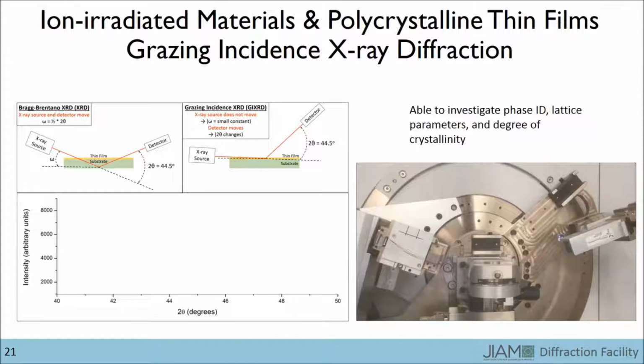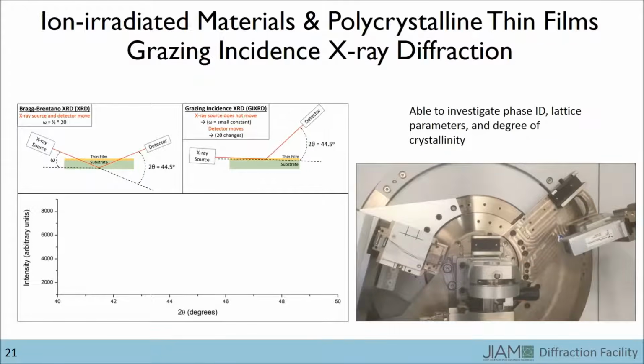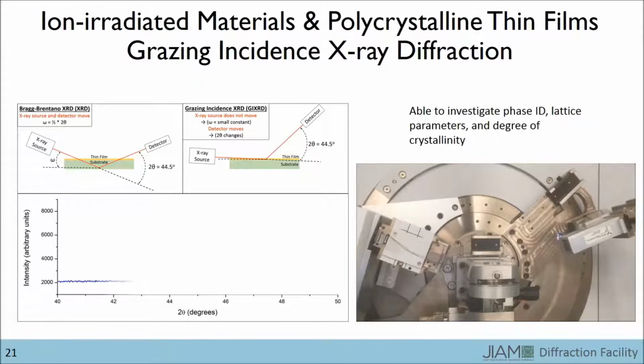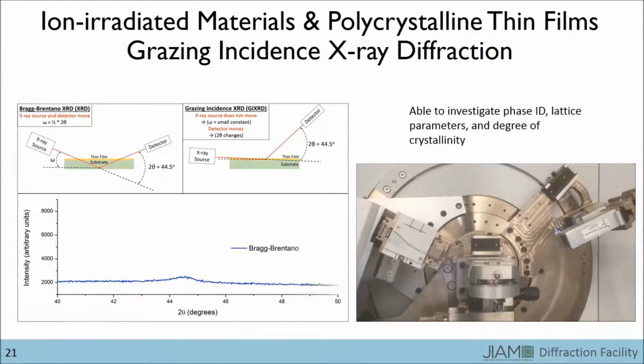Here you see the system in the Bragg-Brentano configuration, so the source and detector both begin at 20 degrees, which makes a starting 2 theta angle of 40 degrees. They then rotate at the same rate upward by 5 degrees, which makes an end angle of 50 degrees. This results in a very weak peak.